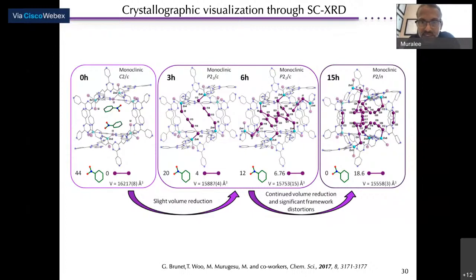This is after 6 hours. Again, you can see the volume changes. Now the amount of nitrobenzene is leaving slowly, you can see, whereas the concentration of iodine molecules found within the pores is increasing over time. And this is 15 hours exposure. And you can see the iodine, now we can even see an I3 type motif also forming. And now after 15 hours, no nitrobenzene is located.